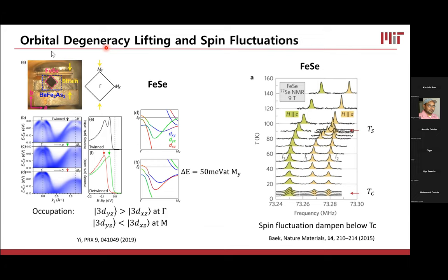Then we have to talk about the microscopics of iron selenide. If we repeat these kinds of ARPES measurements, where we apply strain in order to detwin iron selenide and look at the change in the orbital occupation, then we see something kind of interesting. At the gamma point, we find that the 3d YZ orbital becomes more occupied than the XZ orbital. Again, these are the iron 3d orbitals. But if we follow this out to the M point, we find that the 3d XZ orbital actually becomes more occupied. And there's a pretty large energy gap between the orbitals at the M point. So this is an indicator, again, that there's orbital degeneracy lifting that could play a role in driving the ambient pressure nematicity in iron selenide.